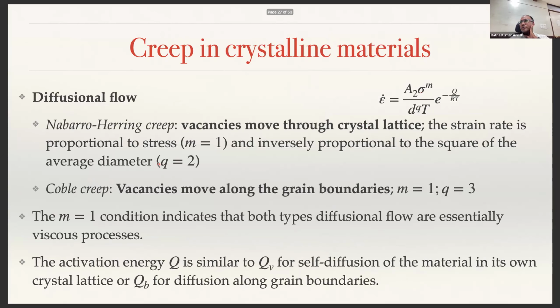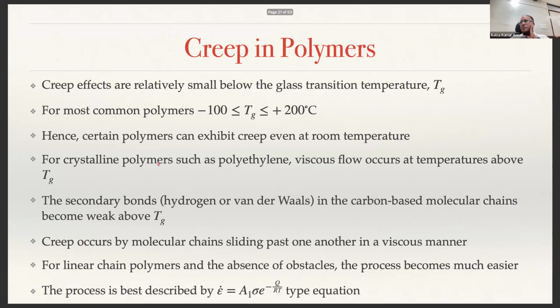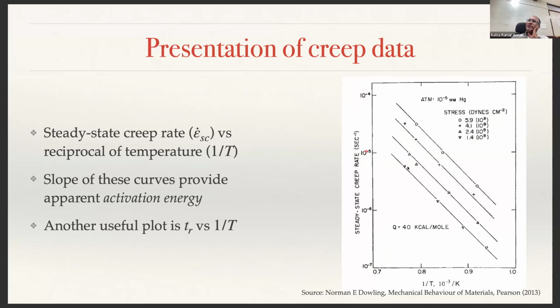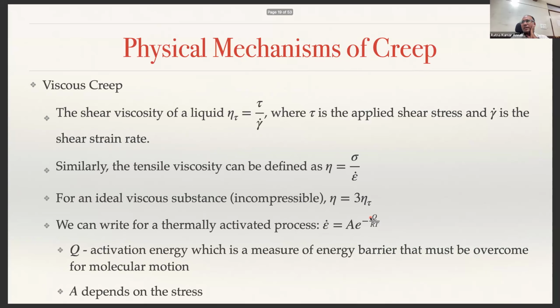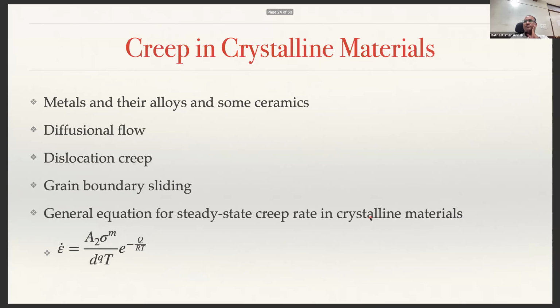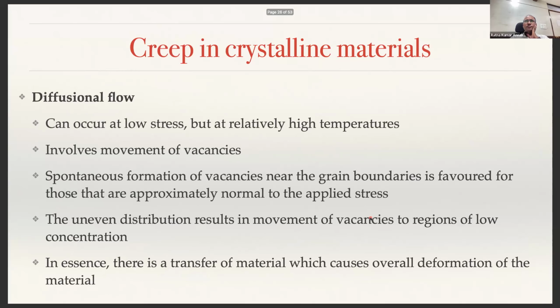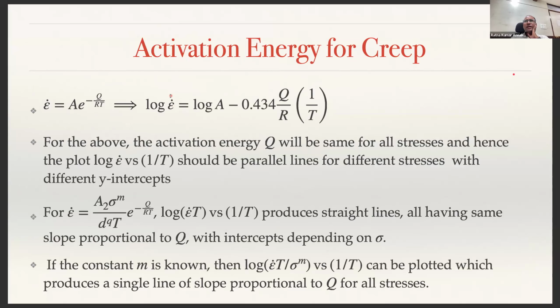That is why steady state creep gives you parallel lines, right? 1 over T versus steady state creep rate. That is what we are seeing here. We are plotting the creep rate, and you will have parallel lines for different stresses with different intercepts. So if you take this equation and plot log epsilon dot versus 1 over T, that will produce straight lines all having the same slope proportional to Q.